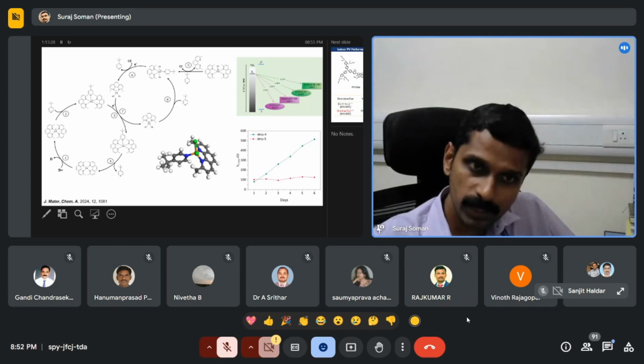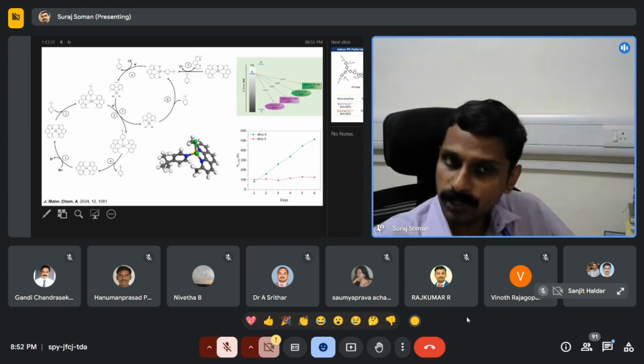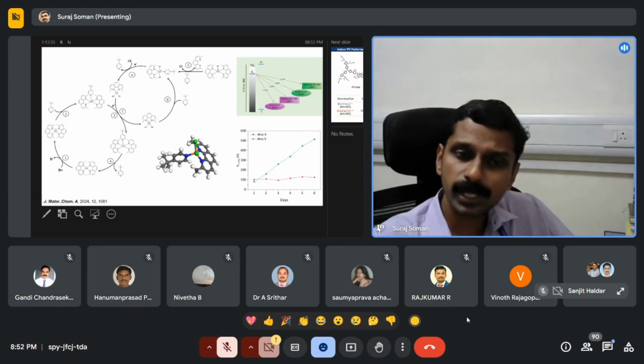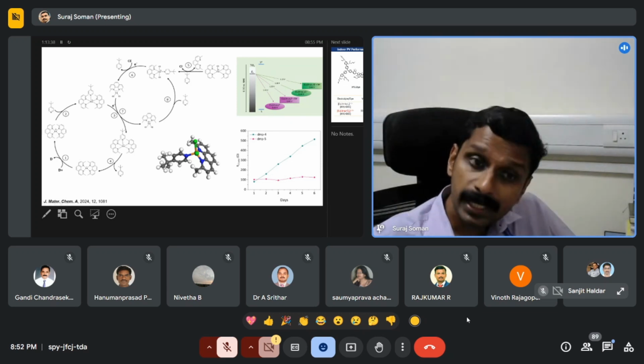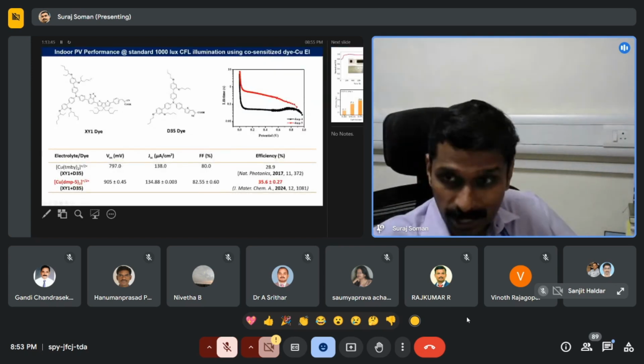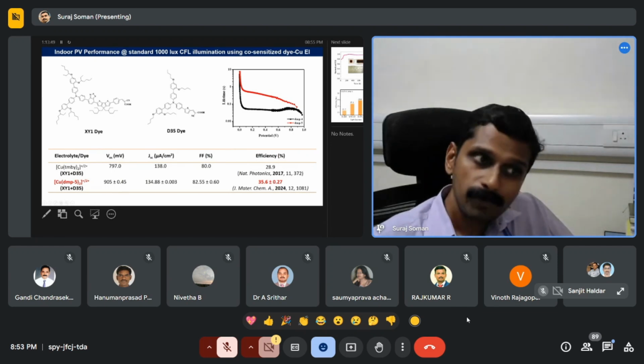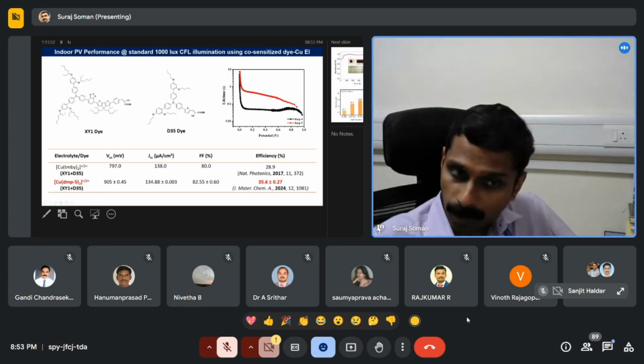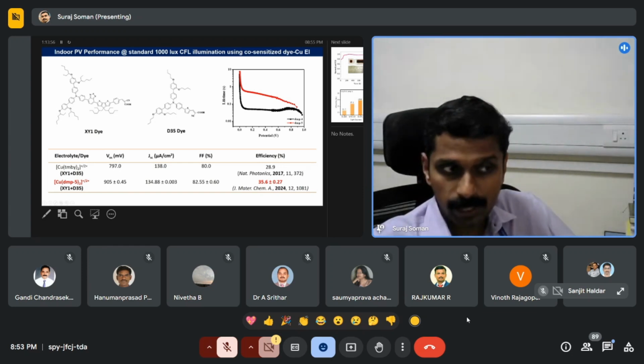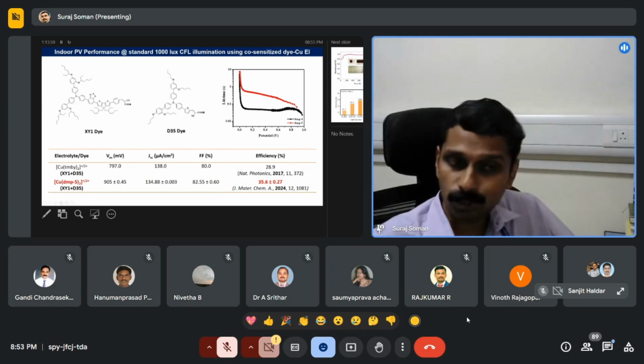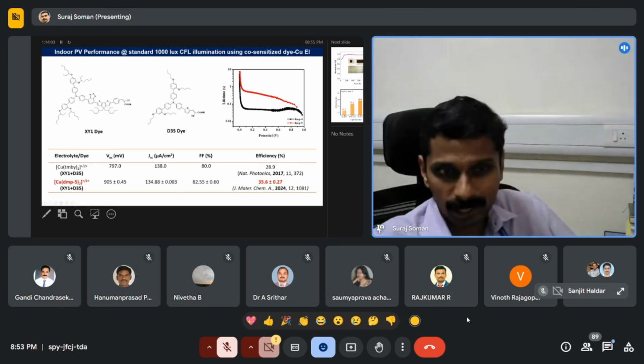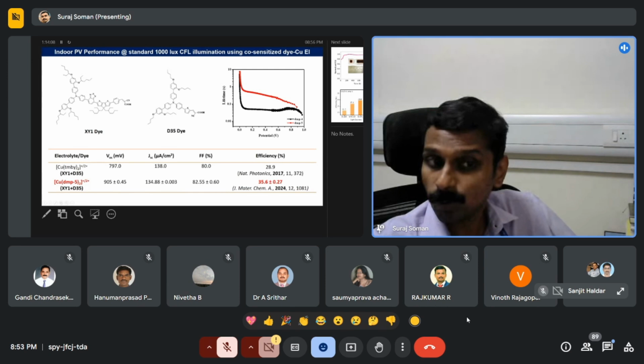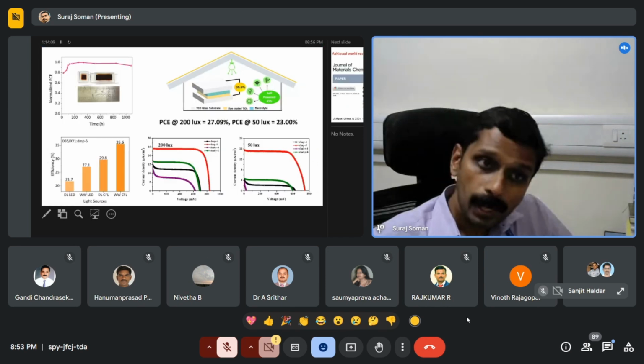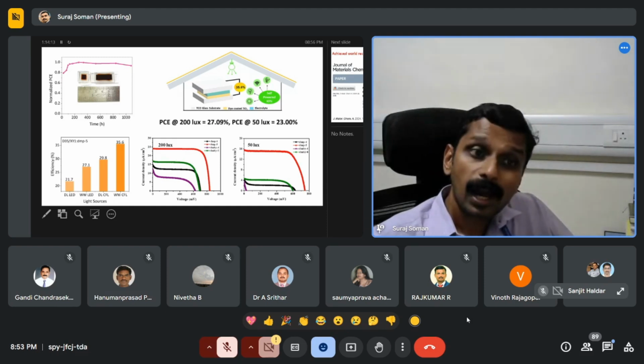We did some dummy cell measurements, and what we have seen is that DMP4 is the conventional electrolyte. So with the passage of time, the charge transfer resistance on the counter electrode side increased drastically. But when it comes to the new electrolyte, it was almost the same. And then we went into the real device, where we used the same kind of dye combination that Michael Gratzel used in the Nature Photonics paper in 2017. And we changed the electrolyte from the conventional electrolyte to the 5-coordinate electrolyte. And what we have seen is an improvement in performance from 28% all the way to 35%. And more importantly, we have seen this improvement under very low illumination conditions like 200 lux, 50 lux and so on.